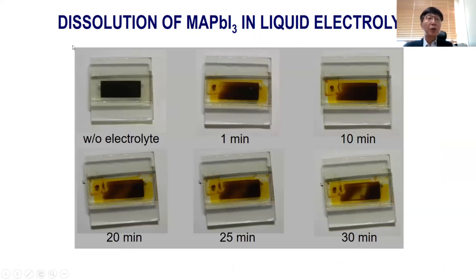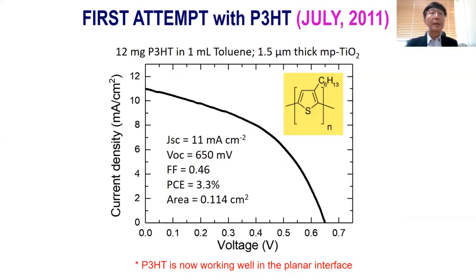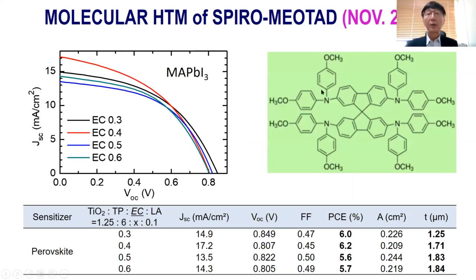However, the big issue is that the perovskite dissolves well in polar liquid electrolyte. Shown here, once you inject electrolyte into the perovskite-sensitized titanium oxide, in a few minutes the perovskite dissolves completely. So I wanted to replace the liquid electrolyte with some solid hole conducting material. The first attempt was with P3HT, but the first trial was not successful because the large polymer material is difficult to infiltrate into mesoporous titanium oxide.